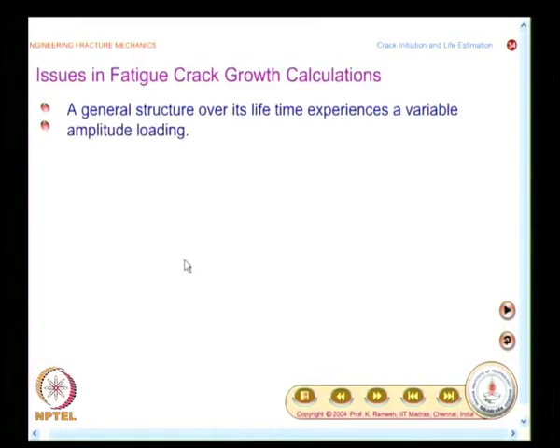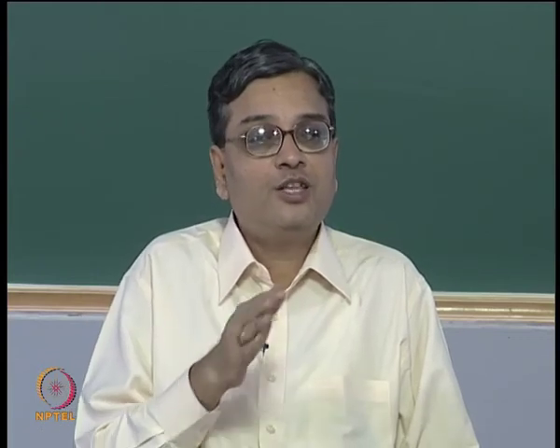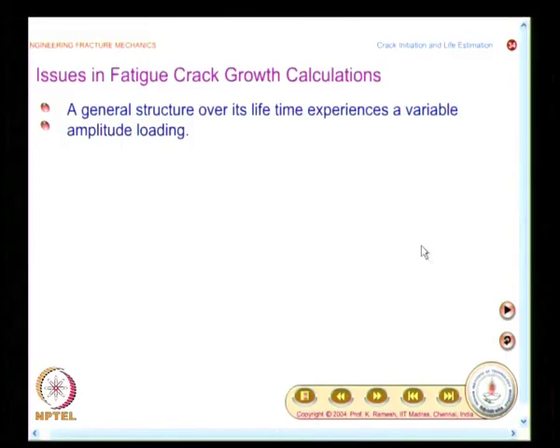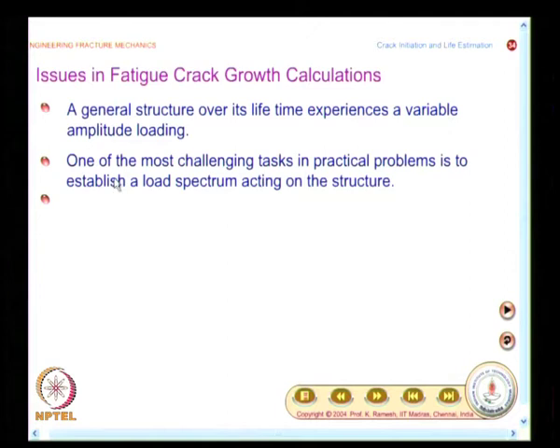And you know, now you will have to look at what are the issues in fatigue crack growth calculations. A general structure over its lifetime experiences a variable amplitude loading. You know, this you have to keep in mind, this is unavoidable. Only from the textbook point of view, you will have a nice sinusoidal loading. When you do the rotating bending test, you will simulate only a sinusoidal loading, which is only for evaluating the endurance limit. In all practical structures, they experience variable amplitude loading, which is unavoidable. And one of the most challenging parts is how to establish a load spectrum.